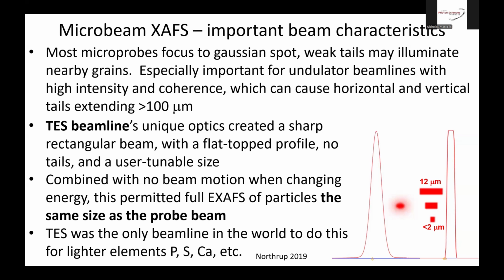So one of the things that made the TES beamline at NSLS2 unique is that its optics were designed to create a sharply defined rectangular beam that had a flat-topped, basically a plateau profile, and no tails, and that it was user-tunable. So you tune it to the size of a particle to optimize it for a particular grain within a sample. And that combined with decoupling the optics from the energy scanning enabled the TES beamline to measure full XAFS of a particle the same size as the probe beam, which was the only beamline in the world that was capable of doing this for the lighter elements. And we hope that when it comes back into operation, it will be able to do this again.